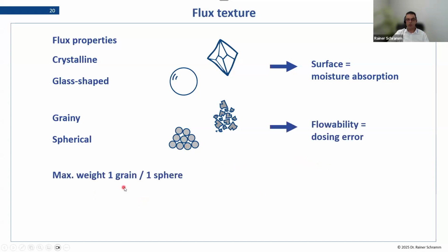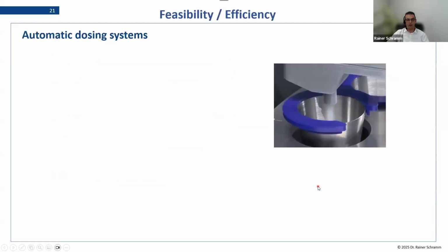In the end, what counts for automatic dosing systems is the weight of one grain. So for example, with our spherical flux, one particle weighs 0.1 milligram. That means I always have the precision, if I dose particle per particle, to get whatever the user wants. If the grainy flux sticks together and one lump is already 1 milligram, then of course I can only have a precision of 1 milligram and not lower. This is something you just have to know to understand how the precision in a flux doser works.